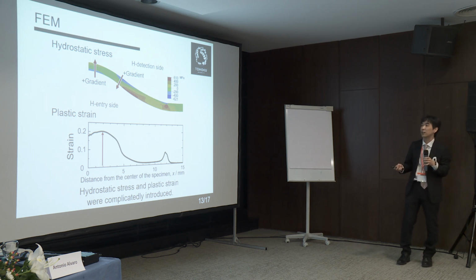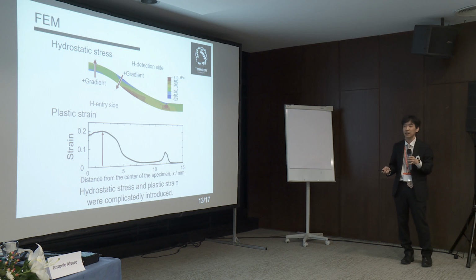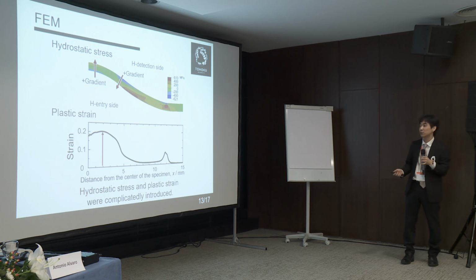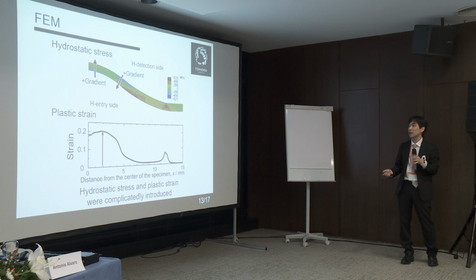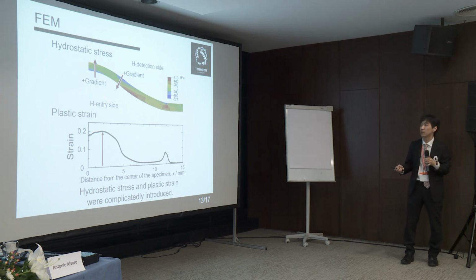These are the results of FEM. The upper figure shows the distribution of hydrostatic stress, and the lower figure shows the distribution of plastic strain. Hydrostatic stress and plastic strain were complicatedly introduced into the specimen. So I will compare them with hydrogen breakthrough time, respectively, from the next slide.